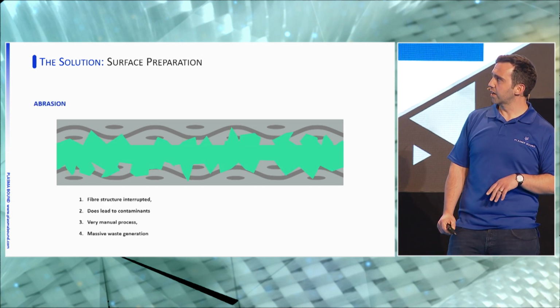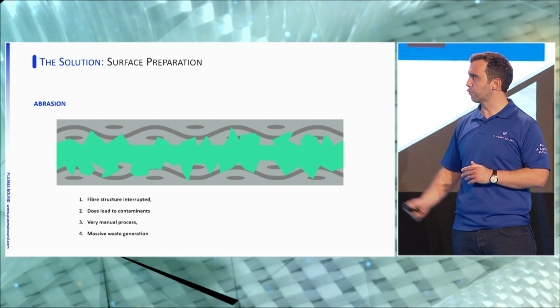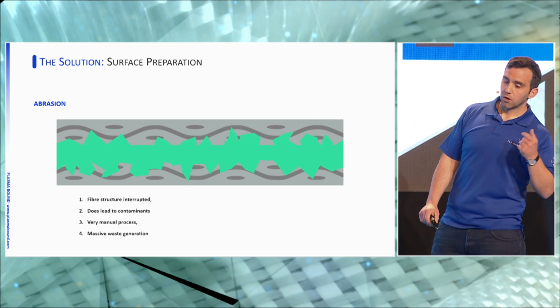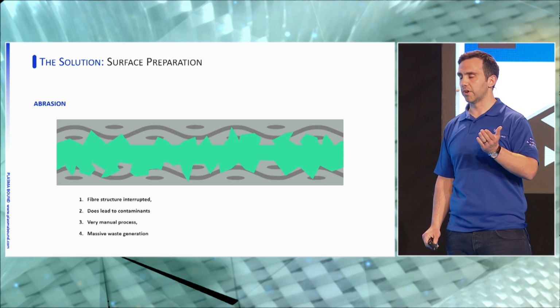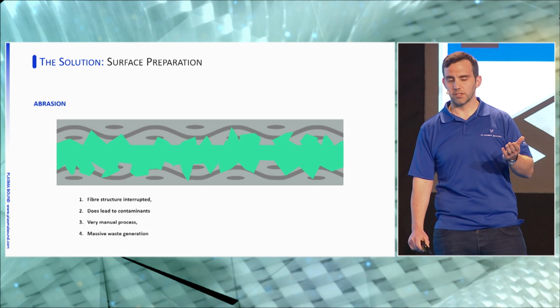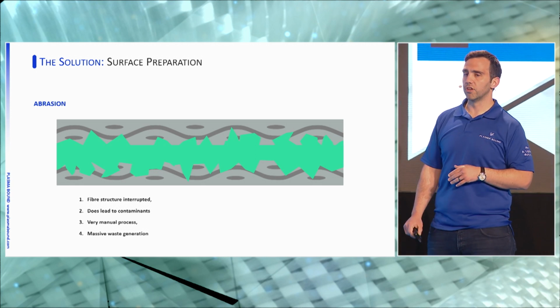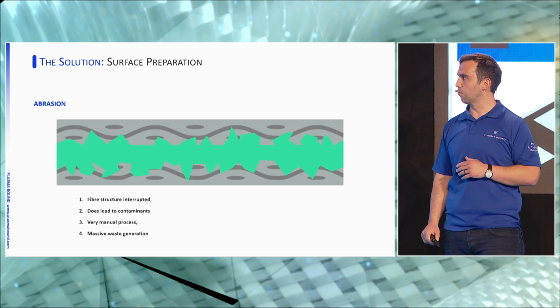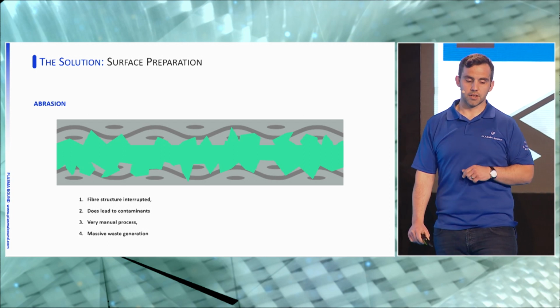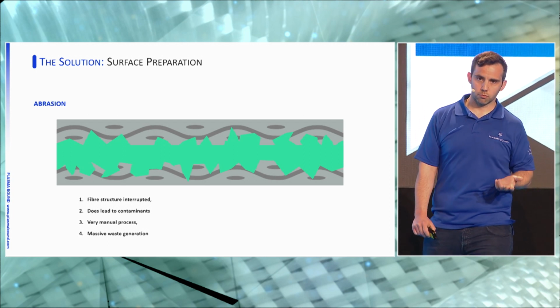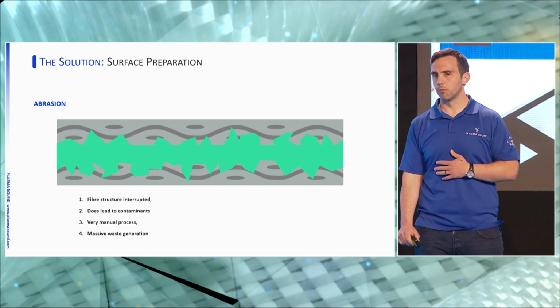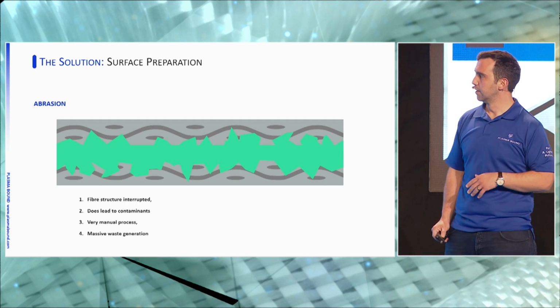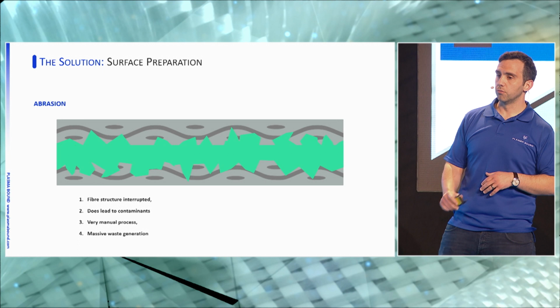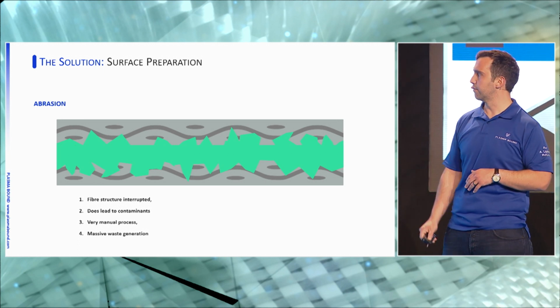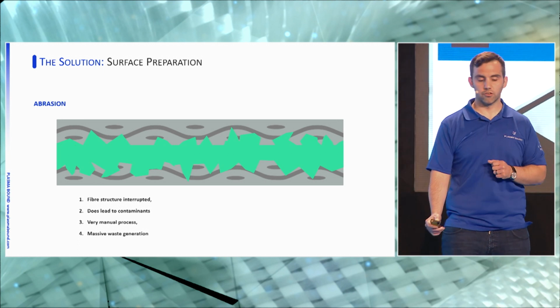So when you look at abrasion, which is hand sanding, it causes a disruption, and you get fiber interruption. What that means is you might have to put in 7 plies in order to just get the effect of 6 plies out of it. So you're inefficient already. You're destroying material as you're working. It does lead to contamination, and therefore it has to have a subsequent wash. And it's a very manual process, usually done by hand, which means it's also very human dependent between different individuals. And then there's massive waste generation.